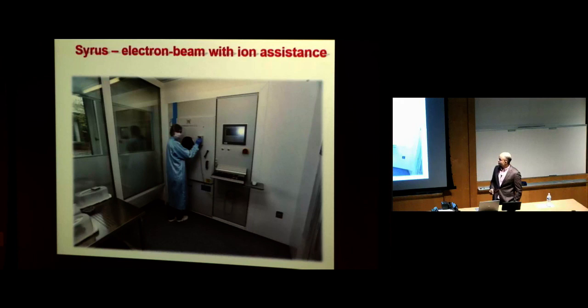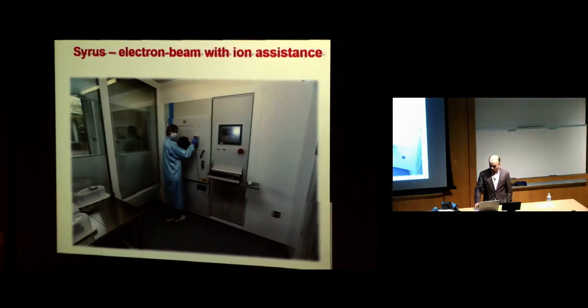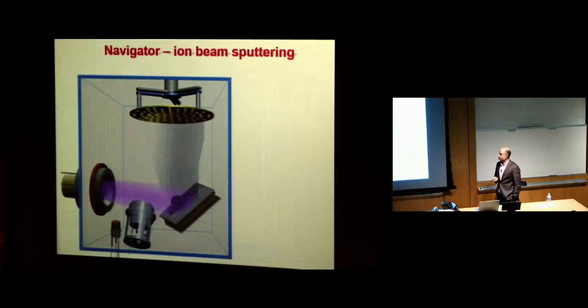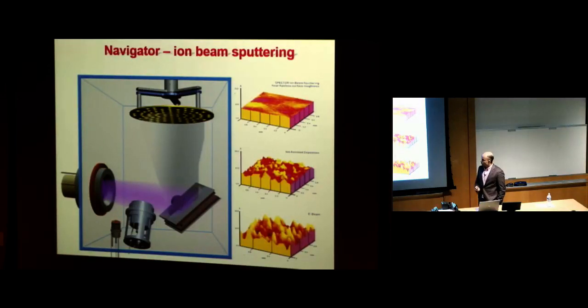That's how these machines look in real life. It's like a box chamber. We have a chamber, here is the door of the chamber, and inside the chamber we have the substrates which we coat. And the third technology, used for high precision optical coating, is so-called ion beam sputtering. In this case we don't use electrons, we use pure ions. Usually we use argon or xenon ions. We send them to our target, and because the ions have quite some energy, our material flies in the direction of our substrate. In this way we can control all the parameters very nicely.